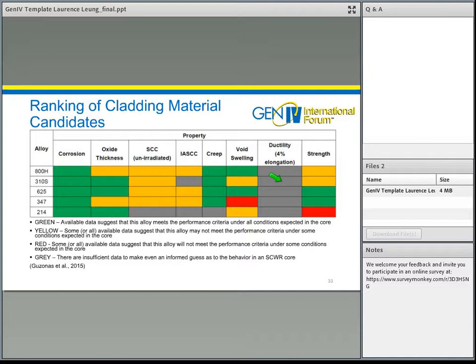So if you look at it overall, for ductility, none of the alloys seems to have sufficient data to cover the ductility property. But you can see that alloy 800H and 625 seem to be the best, with sufficient information to justify them as good cladding material candidates.